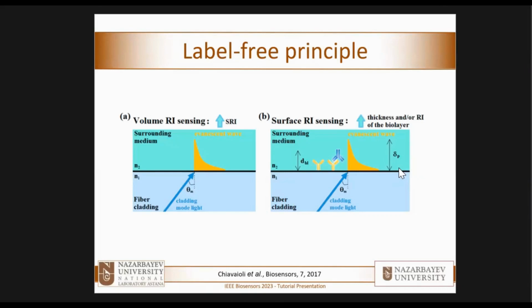It is also quite important to consider the role of the medium. The underlying physical assumption of all optical fiber biosensors is that the medium in which they operate is low loss, such as blood, urine or sweat, but not saliva, because saliva has particles that make the medium highly scattering. That's why detection in saliva is much more complicated.